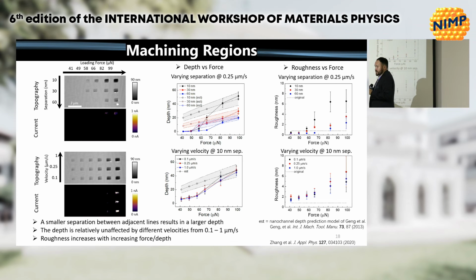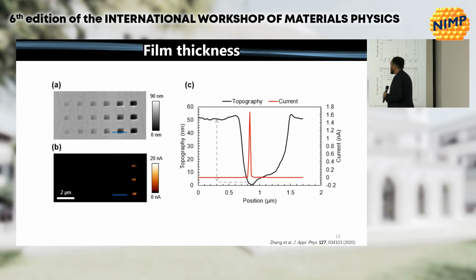Okay, this wasn't recorded simultaneously. It was recorded after the fact, but in principle, you could be measuring current as you're doing the measurement. So the diamond tips are doped, so you could be removing material, measuring current as an indication or even a feedback of when you've reached the film, or you start to even sense the layer underneath if you don't want to go through the film. So that's also shown here. At the time we hadn't had TEM of this, so we didn't actually know the film thickness precisely, and so this correlates with what we saw: around 50 nanometers is when we start seeing conductivity.